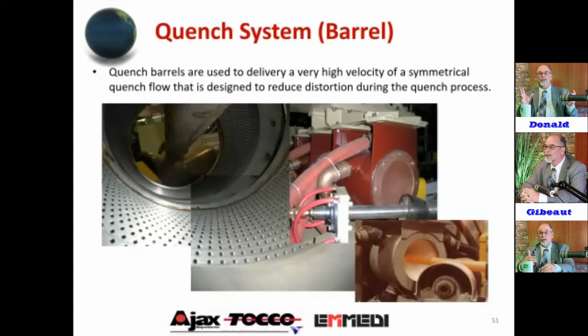And I went to their barrel and got their permission to take it out because this inside is a sleeve that's replaceable that has all these holes in there. And I was looking for that condition of plugging our holes, and Tenaris, the operators, their maintenance group, everybody said, we don't have problems. That quench barrel's been in there for 12 plus years. So I took it apart and analyzed it in the field. And some of the holes were washed a little bit, but there was no material. The inside was just as clean as the day we provided it. So if you use a cyclonic filter in the pit and that fine particulate matter filter right before the quench headers that we design, you get 12 years out of one of these rings.